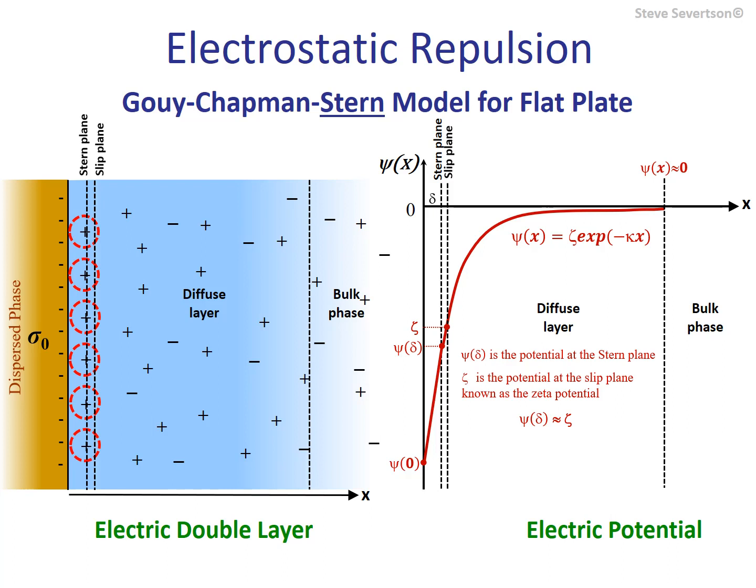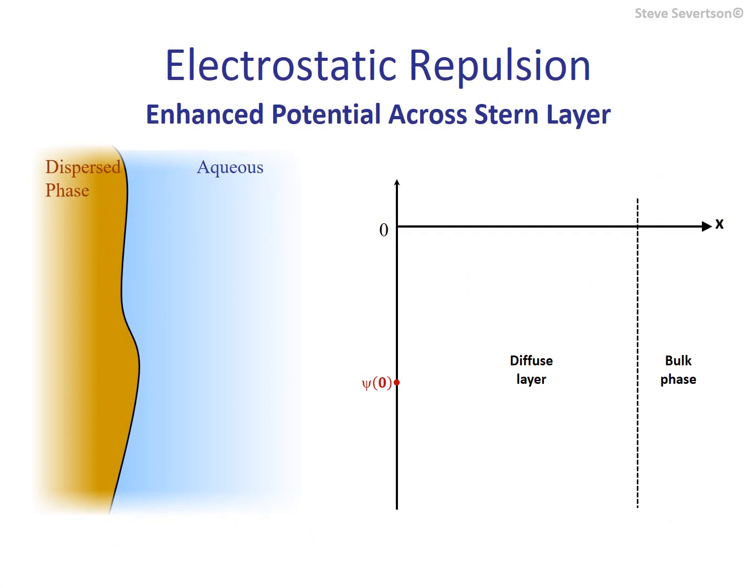This result is important because the zeta potential for a colloid can be measured. The surface potential cannot, and we are most interested in EDL overlap, which primarily involves the diffuse layer. Also note that the zeta potential can be related to surface charge of the diffuse part of the double layer. This can be thought of as the charge density that must be neutralized by the diffuse layer. In addition to connecting electrostatic repulsion to an experimentally measurable quantity, it could be argued that the use of zeta potential also provides a more practical gauge on the influence additives have on colloidal stability.